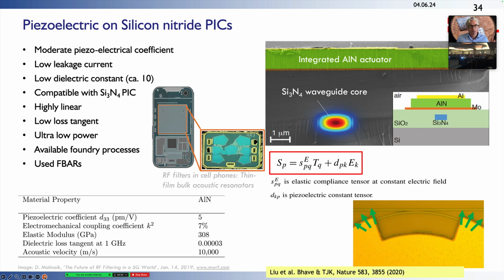In fact, you can generate acoustic waves up to gigahertz frequencies with this actuator, and this is also the reason why it's being used in cellular phones, through the pioneering work of Ruby. And so we have combined these piezoelectric aluminum nitride actuators with photonic integrated circuits, and the actuation principle that we use here is the so-called stress optical effect. The piezoelectric actuator is removed from the optical waveguide that carries the optical light. And what is being used here is simply the stress generated by the aluminum nitride actuator, which creates a stress optical effect, so a refractive index change in the silicon nitride.